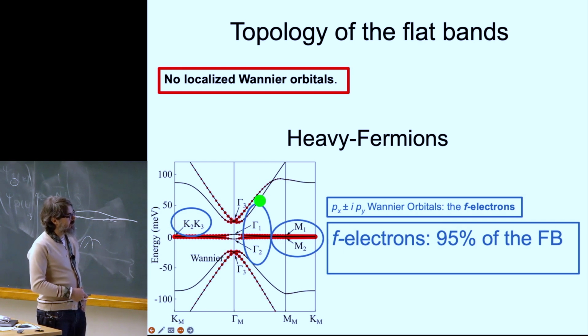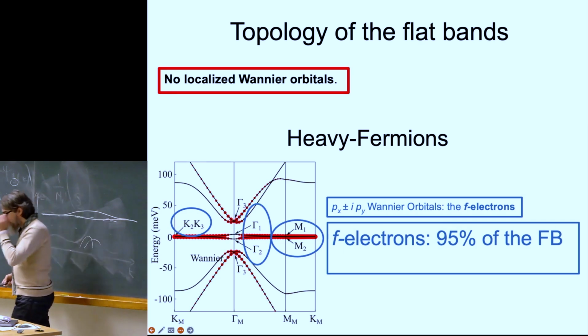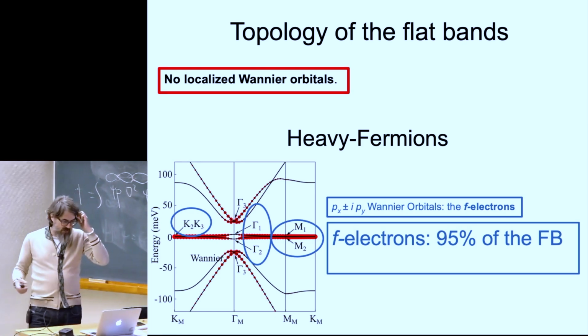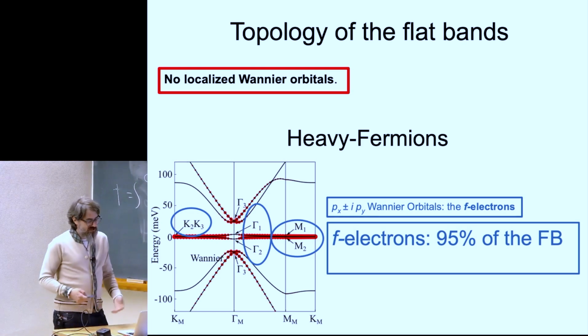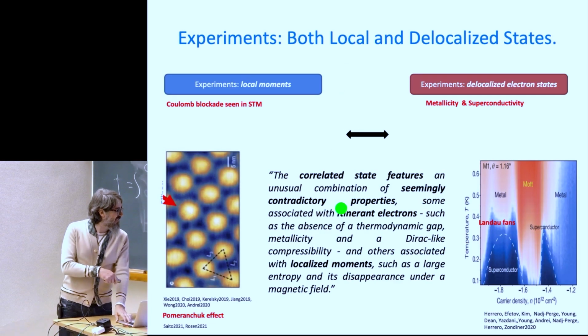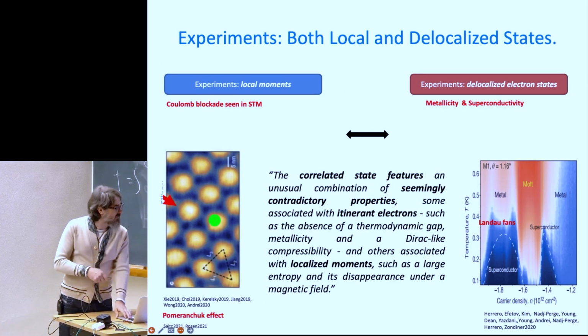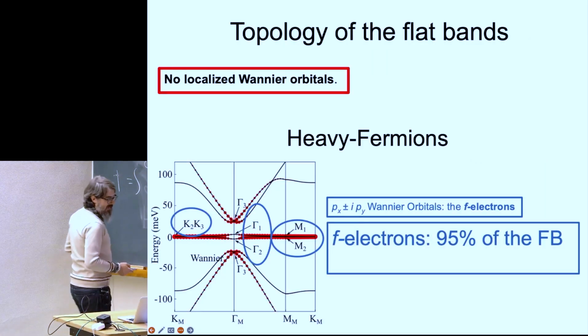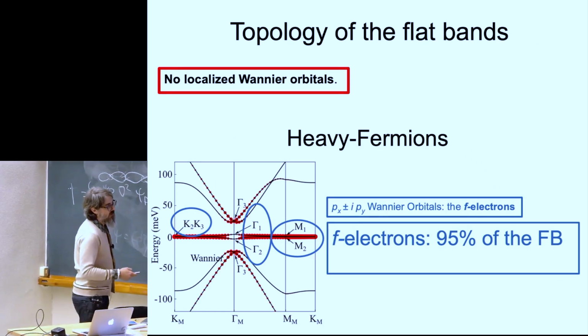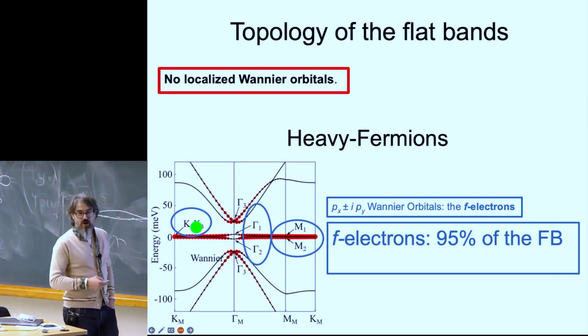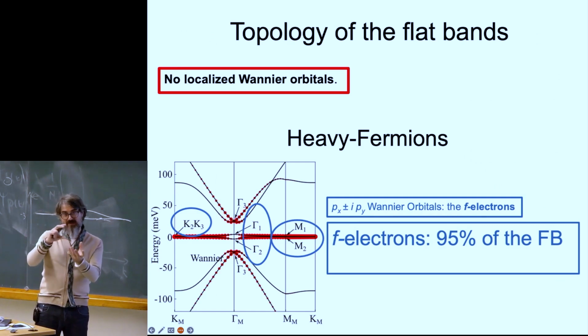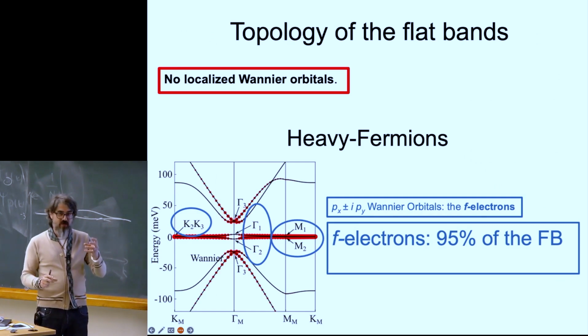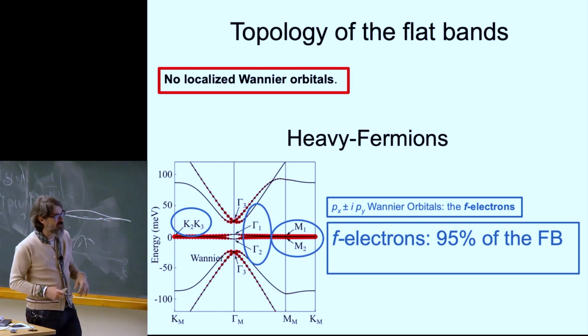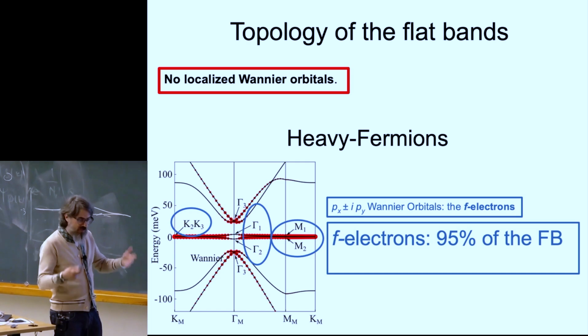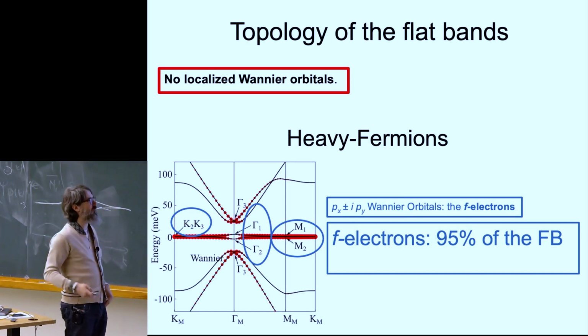So now we know that these bands are topological, and remember what I said at the beginning: topological bands cannot be described by exponentially localized Wannier orbitals. But we also know by experiment that it looks pretty localized. So what's happening? Well, what you can do is build orbitals that are localized at the triangular sites of the Moire. The Moire has a hexagonal lattice, but you can build localized orbitals at the triangular sites, which is exactly where those large dots are. These are effective orbitals. They're made of thousands of carbon atoms. You can write them down as some envelope functions.